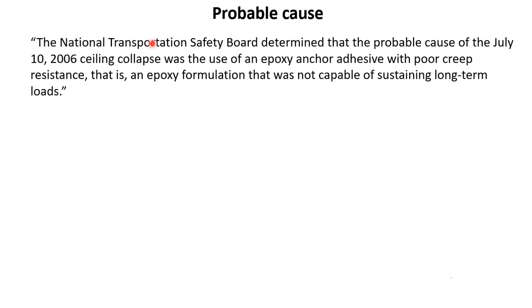So probable cause. The National Transportation Safety Board of USA determined that the probable cause of the July 10, 2006 ceiling collapse was the use of an epoxy anchor adhesive with poor creep resistance. That is, an epoxy formulation that was not capable of sustaining long-term loads. So we can see that during the manufacturing, several decisions were made which were not correct. Decision about how the bolts should be fixed to the roof concrete, what kind of method should be used, and once the decision was taken about epoxy, then inferior quality of epoxy was used, and previously the design had recommended steel and concrete ceiling, whereas later it was decided that precast concrete should be used, which weighed 2.5 times more than the original design ceiling. So all these wrong technical decisions led to the failure.